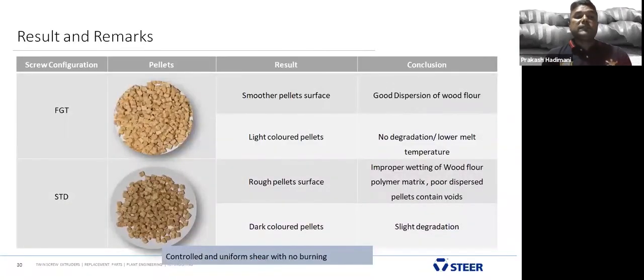See here, this is FGT pellets and standard pellets. FGT pellets give a smooth pellet surface and are light in color, a natural color. And we observed the physical appearance. We observed good dispersion of the wood powder in the polymer matrix. We didn't find any degradation on the pellets.